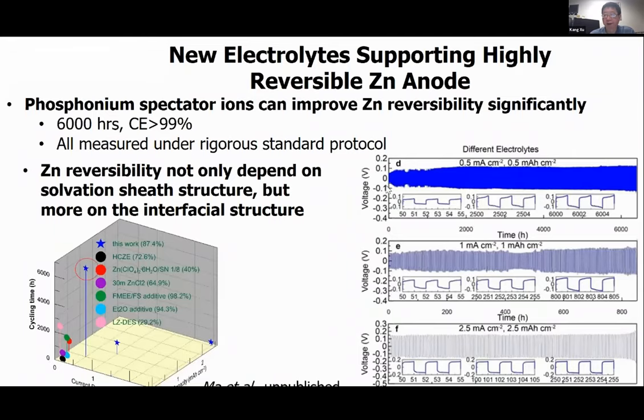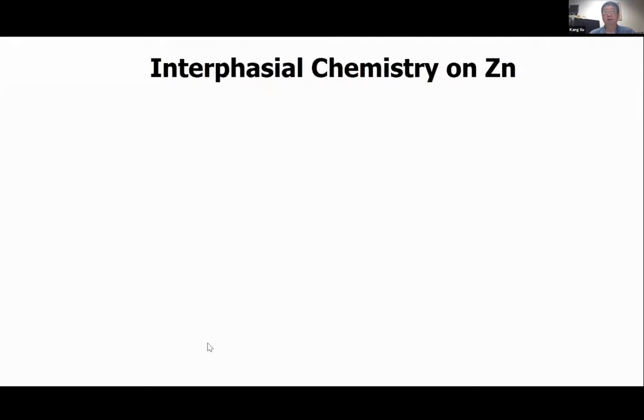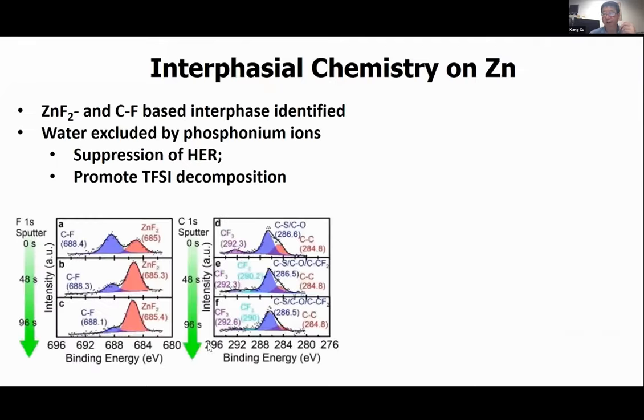And for reversibility, we found that it depends not only on the solvation sheath structure, but also very much on the interfacial structure. On this 3D diagram I show here, this star represents our work. So far, this is the only known aqueous electrolyte for zinc which can survive the 2.5 milliamp per square centimeter current density, along with the 2.5 milliamp hour per square centimeter area capacity goal. But the cycling time is still not very high, about 300 hours in total. We want to increase this by at least 10 fold, and we need to further tailor the surface. We found that interfacial chemistry plays a major role there on the zinc.